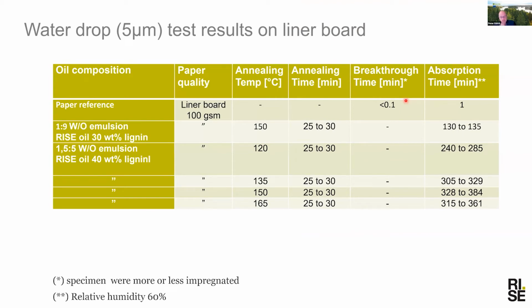When we look at the liner as a pre-test, we would have a breakthrough of the water drop immediately. When we put on the lignin emulsion, we didn't have a breakthrough immediately or at all, but we would have an absorption time. And what we can see is that with 30% lignin, comparing 150 to 150, we had quite a lot better results with 40% lignin. So the lignin content here is quite important.